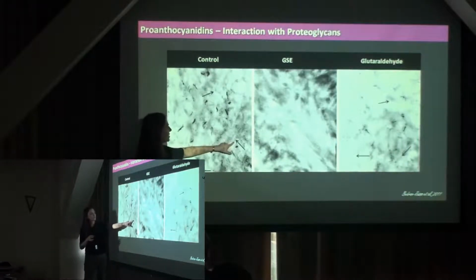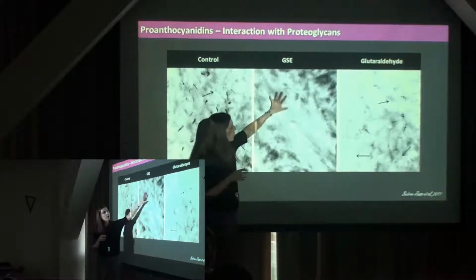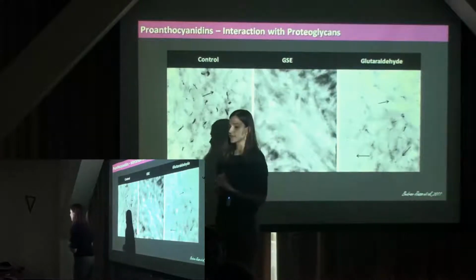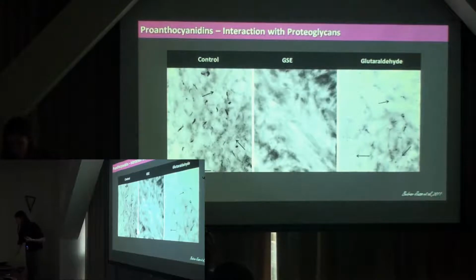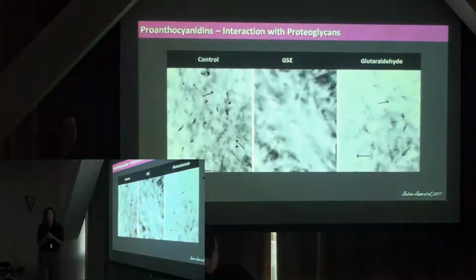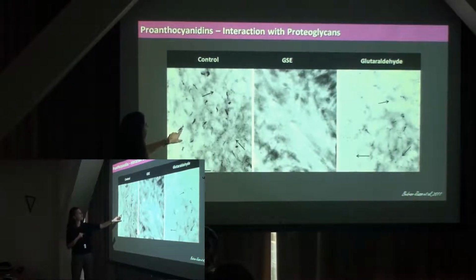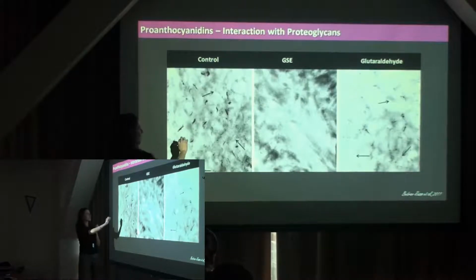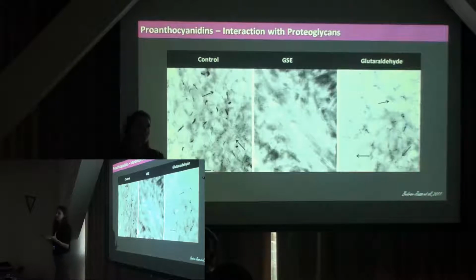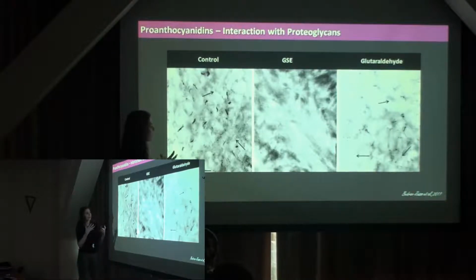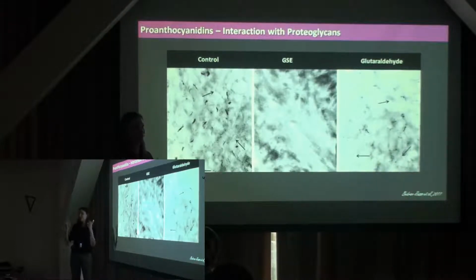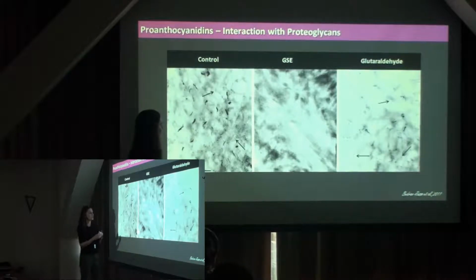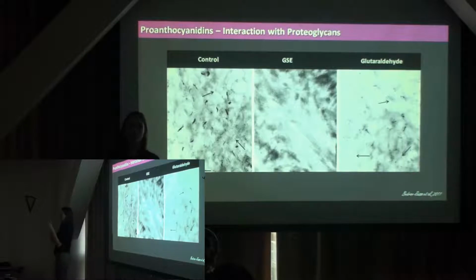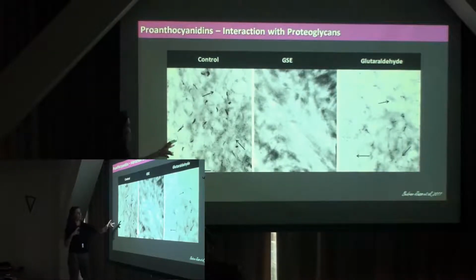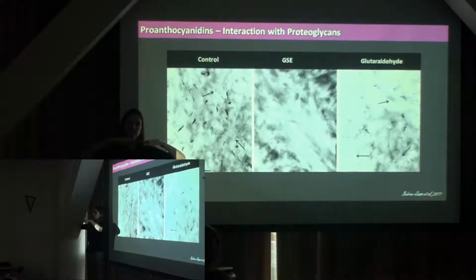So right here, and it's tough to see, basically these GAGs look like little hairs over the collagen fibril. They're all gone here. And glutaraldehyde, we use as a positive control for our studies. If you go like these black areas, what are those? It's either part of the sectioning or they were concentrated. We used a cuprolinic blue stain, so it could be something related to the staining technique. We did this with bovine teeth, which are bigger, so you can appreciate more, but we had to prove this in human teeth too. If you look at it, it looks just like hair over, and it coats these collagen fibrils. So there's enough water that it keeps the collagen expanded and hydrated.